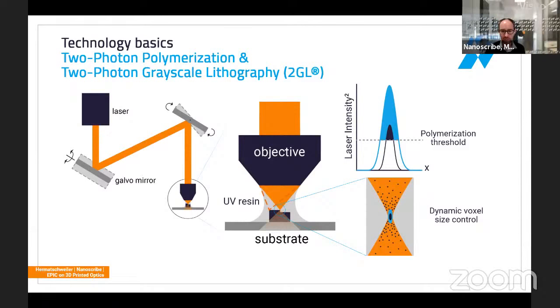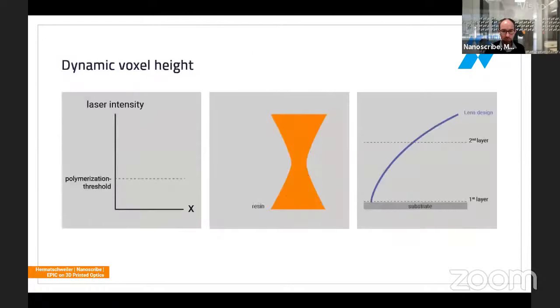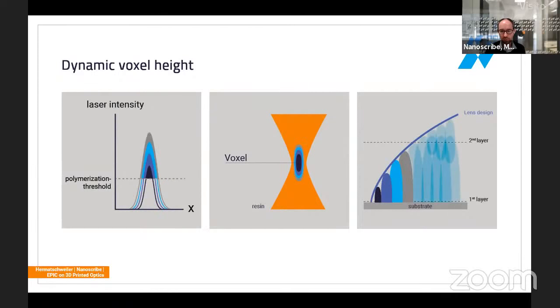And that's based on the fact that you can tune the laser focus and the size by increasing or decreasing the laser intensity in the laser focus. And if you do that electronically well controlled, you can do this on a 100 nanometer grid as we do it. And this results in the ability to form, for instance, a curved surface with just one slice. And this reduces the print time excessively, and it results in optically smooth surfaces.